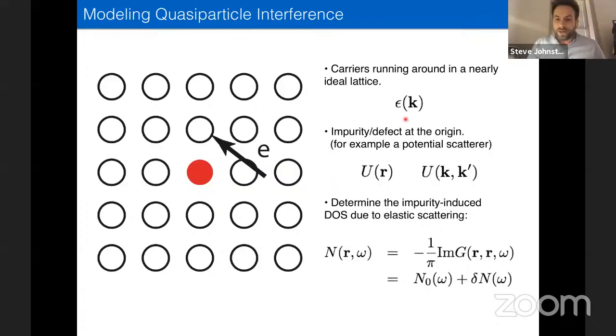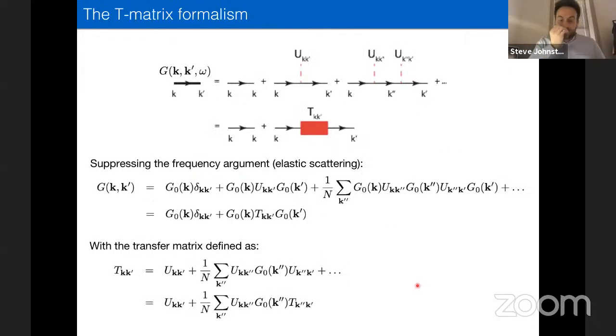The idea is that we're going to introduce some non-interacting band structure. In this case, I'm just going to take the DFT bands that were calculated by Hanke's group. We introduce into the problem basically a single impurity, so some impurity potential U(r). In k-space, it breaks translational symmetry, so you have a k prime argument. And we're essentially going to compute the interacting Green's function in the presence of this impurity, and then the imaginary part of that gives us the densities in the system.